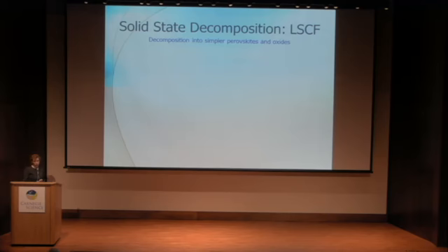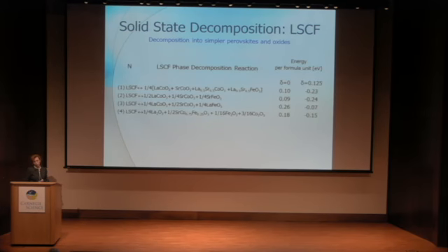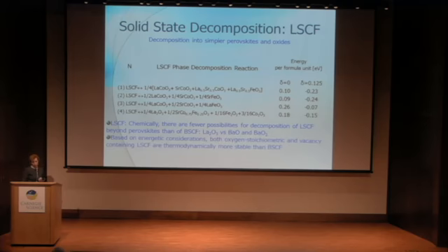The same kind of reactions we tried to do for LSCF. It turned out that there are fewer reactions in comparison to BSCF which are possible here, and energetics of these reactions were also different. So chemically, there are fewer possibilities for decomposition of LSCF beyond perovskites than of BSCF, and it depends on possible oxides and combination of perovskites which can be a result of this decomposition.